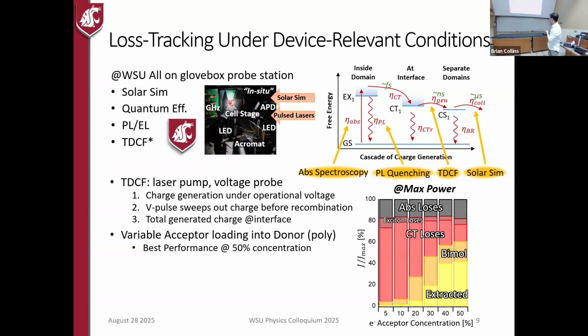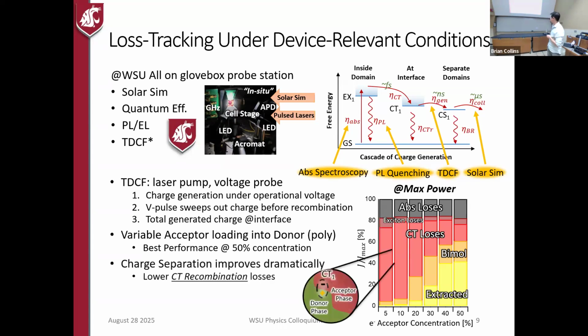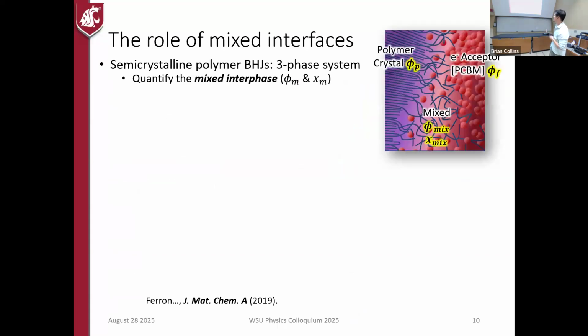But we can see that the big change here is the losses in this charge transfer state that we're affecting. And so the question is, what morphologically is happening at the interface to allow for better charge separation at this point? So there we turn to our X-ray techniques to characterize the nanostructure of these devices.